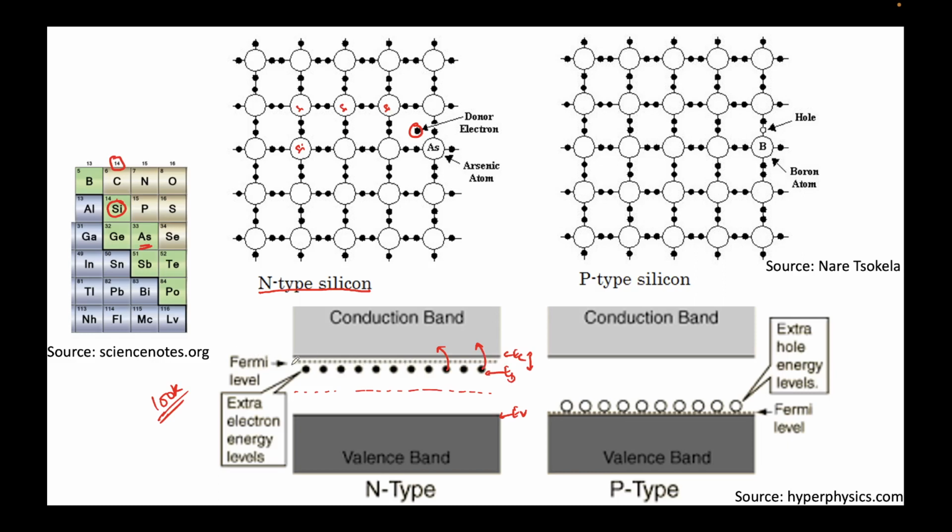And since the Fermi level, you see the Fermi level shown by this black dotted line here, we know statistically is the energy level at which the probability of finding an electron is half. So at 0 Kelvin, all the electrons will be bound with arsenic. Hence this is the state that we see, all filled in Ed. All electrons are in the Ed state, and the conduction band is obviously empty at 0 Kelvin. Statistically, the Fermi level will lie at mid gap between the two. Hence Ef will lie somewhere between Ed and Ec in n-type silicon. So we have determined that in n-type silicon, in this case doped with arsenic, Ed, the dopant level, will lie above the mid gap level and close to the conduction band, and the Fermi level will lie somewhere between the dopant level and the conduction band level.